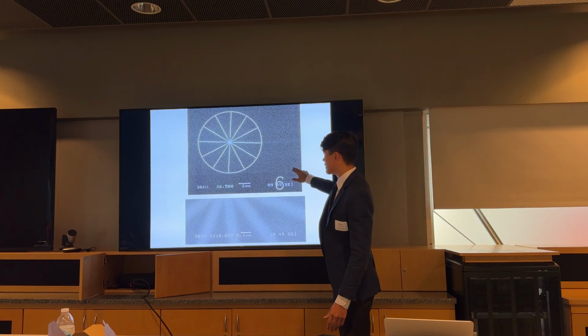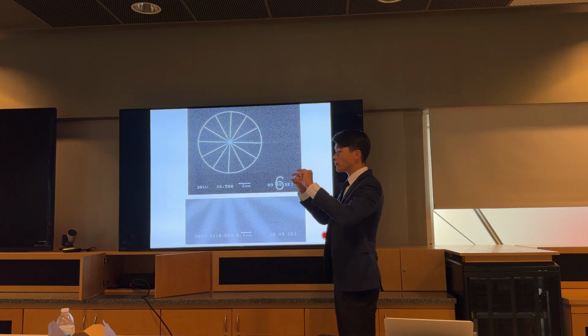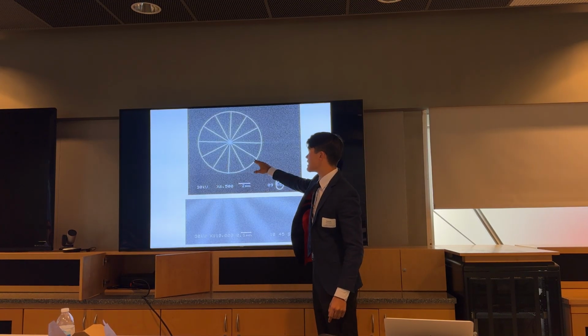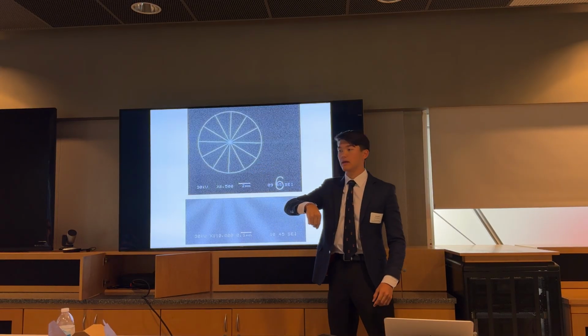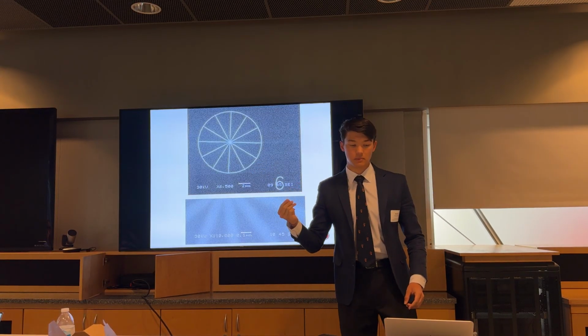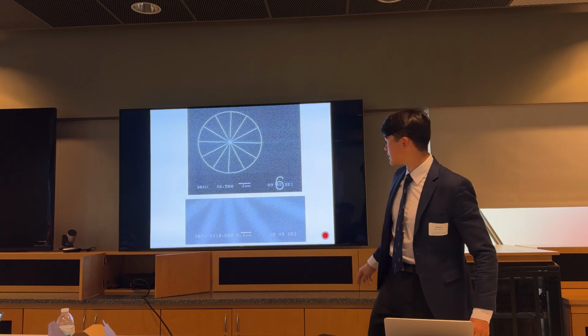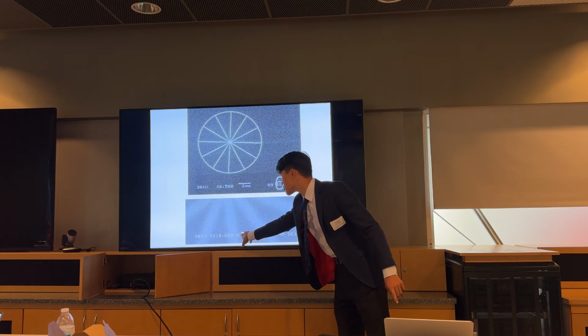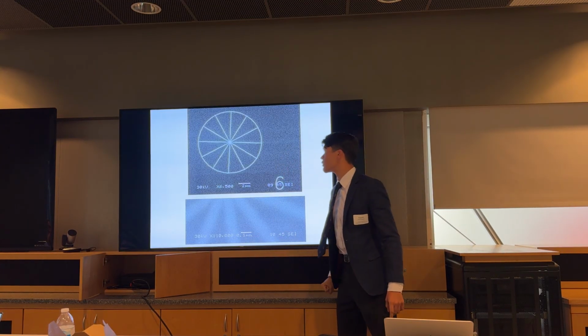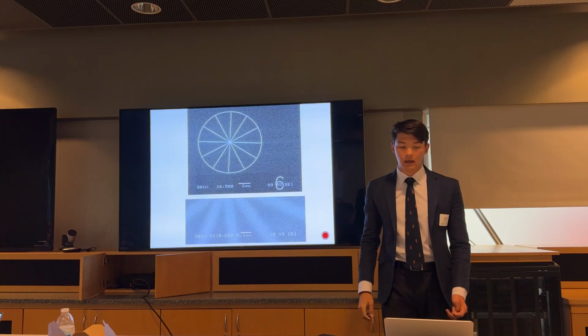Any dark area is a layer of silicon coated by PMMA that has not been removed and developed. And any light area is an area where the PMMA has been exposed by the electron beam and subsequently removed. And you can see down here by this 100 nanometer scale bar, I achieved a line width of about 100 nanometers.